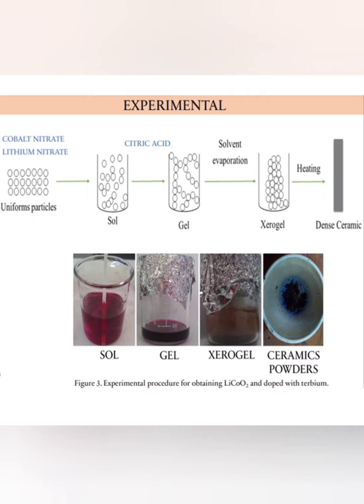The drying was at a temperature of 110 degrees to eliminate the remaining agents, and a heat treatment at 800 degrees during 24 hours to obtain a dense crystalline ceramic.